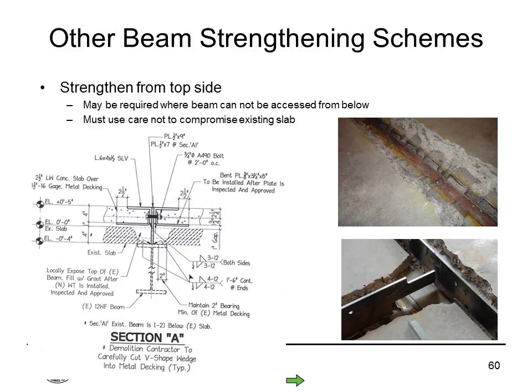So this is an example of where we reinforced existing beams from the top side in New York, where we're on the second floor and we weren't able to access the beams below. In order to accomplish this, we had to cut through the slab from the top side very carefully to expose the top flange, and then as the demolition contractor worked, as soon as they removed a small portion, they welded the deck back to the existing beam. And then we installed a system of reinforcing plates and angles, and a new slab that basically raised the existing slab. So it's a lot of work, but sometimes you may need to use a procedure like this if you don't have access to the underside of the beam.